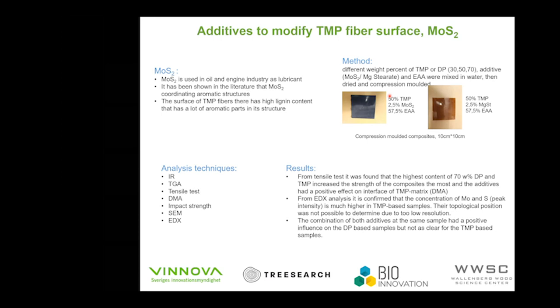So some very brief results here. From the tensile test, we had the highest strength at 70% of DP or TMP. And from the DMA test, we found out that the additives have a very positive effect on the mixing of the fiber and the polymer. The EDX analysis, which I will show you on the next page, confirmed our theory: the peak intensity of molybdenum and sulfur was much higher in the TMP-based samples.